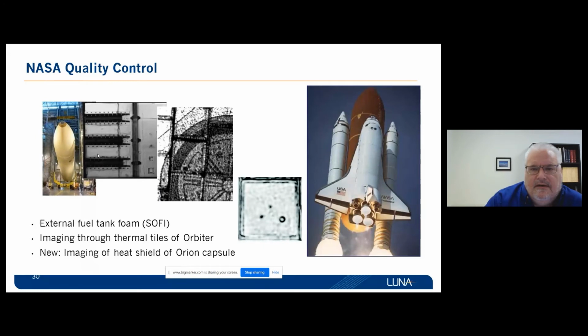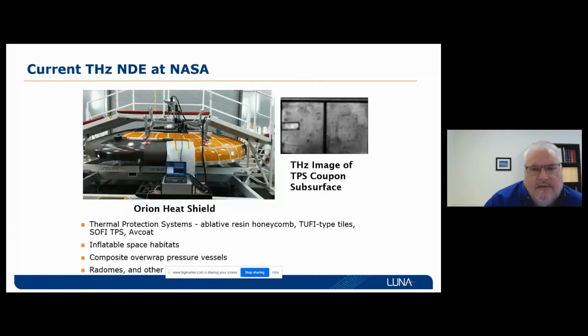One of the issues was that as these orbiters age, which of course are now museum pieces, NASA actually only knew the location of certain features they might have to access down to about an inch, which meant that in some cases they had to remove more tiles than were necessary. And each tile was tens of thousands of dollars to remove and replace. So in the last dozen or so missions, they did save a lot of money using the terahertz system, and presumably as we go forward with more reusable spacecraft, this can be done as well.